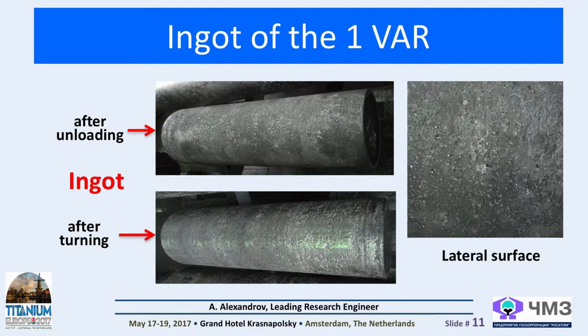It also was a new moment for such kind of alloys. The ultrasonic control of the head parts of the ingots confirmed the absence of a shrinkage cavity. The next moment, taking into account the big diameter of the ingots and their enlarged weight, the cooling was selected consistently in vacuum and in the environment of helium in order to prevent the formation of cracks on the top end of the adjacent lateral surface of the head parts with a sharp change of thermal load, for example, cooling or heating.